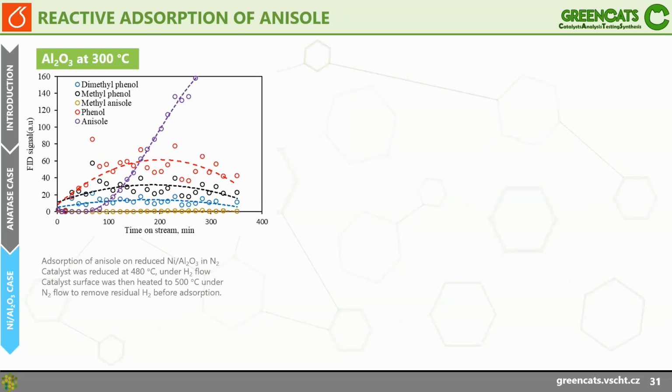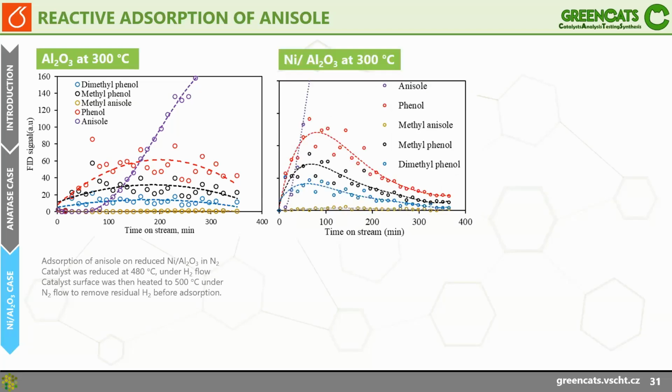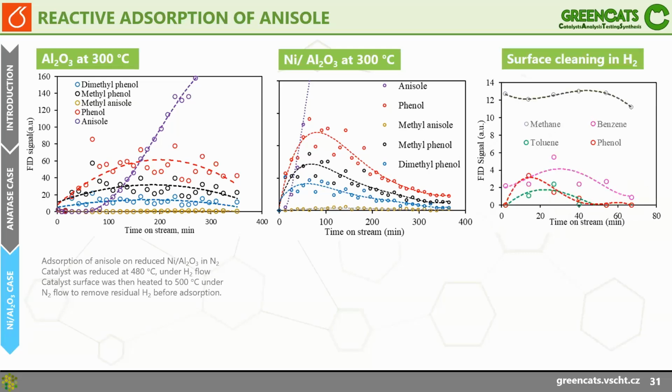And that caught our attention, because suddenly we could see the methyl is not lost, not going to form methane as a not so valuable byproduct, but we can keep it on the aromatic ring in this case, because we have methyl phenol, methyl anisole, dimethyl phenol here as products in different quantities. And the distribution looks fairly similar when we have nickel on alumina. So seemingly the role of alumina in this case is quite significant.